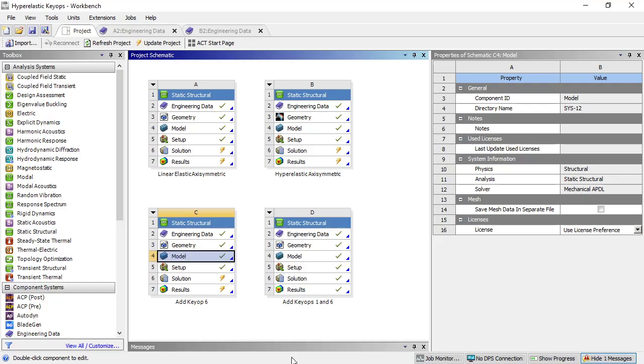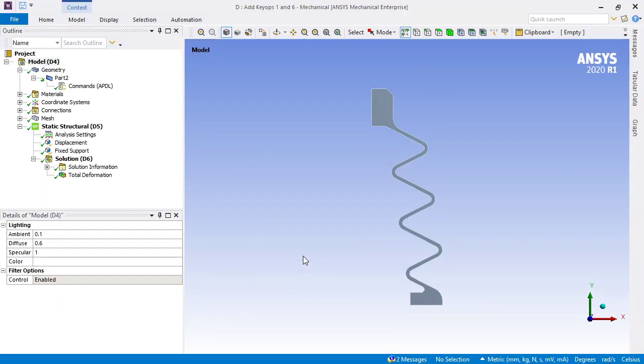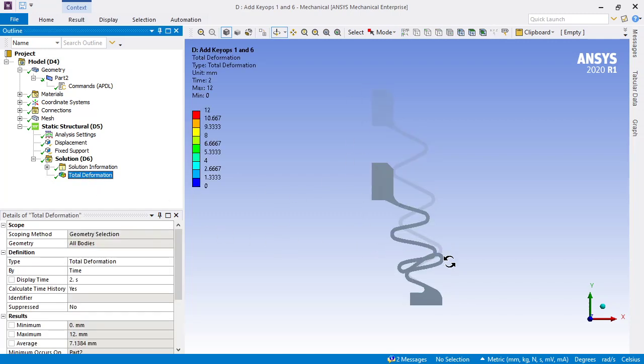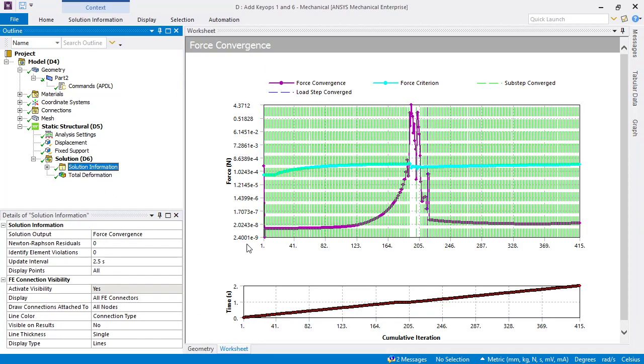When that is done, as in this last model here, you will see that we succeed. In fact, we succeed not only in getting up to 9 millimeters, we succeed in getting all the way up to 12 millimeters. We could have kept going. It had some difficulty just before getting to 9 millimeters, but it kept going and then went all the way out to 12.